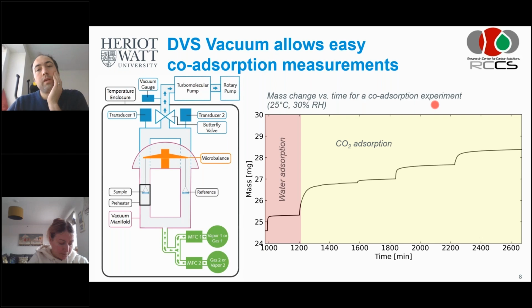Sorry. Well, what we do is vacuum and heating to 70 degrees to already remove as much water as we can, but that's definitely not enough. So a lot of the water will actually desorb together with the CO2. So we go to 100 degrees C at a vacuum of 0.1, 0.2 bar, more or less, 0.3. So these are the regeneration conditions.